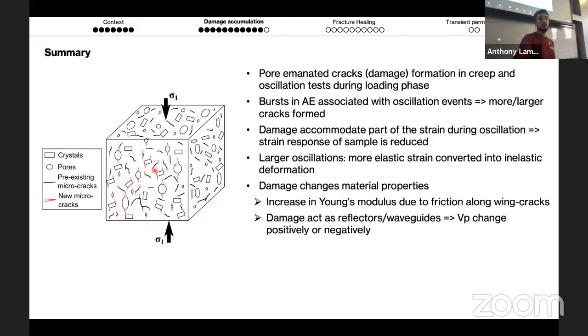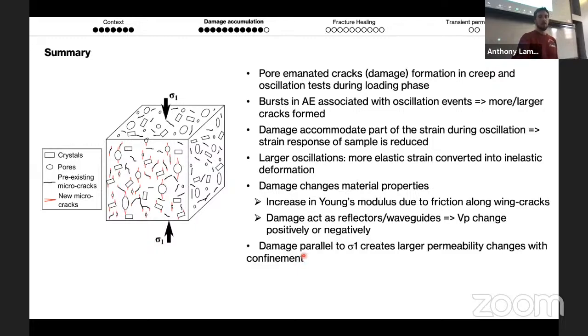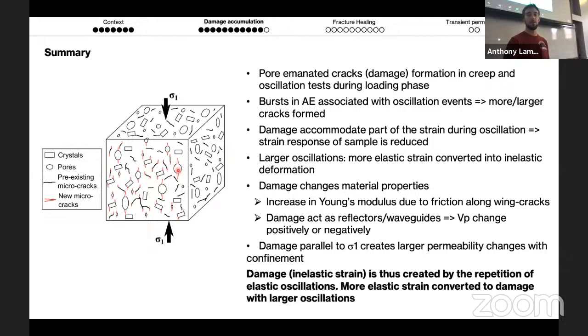So we have Young's modulus that is increasing due to these cracks having frictional resistance during unloading, but also, depending on the size and the orientation of these cracks, we will have a more drastic change in VP with more damage. And if we apply confinement perpendicular to these cracks, they will close more if you have more of them, and therefore you have a larger permeability decrease with confinement. What's important though is that here what I show is that the damage, or the inelastic strain, is being created by the repetition of these elastic stressing events.